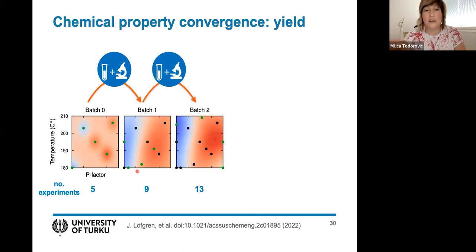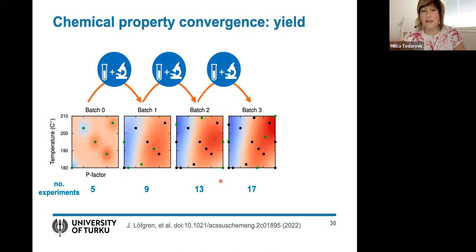So then we performed these four experiments, we added it to the model, and now you can see how this model differs from the previous one. The area of high yield is basically moving up in parameter space. So once again, the black points are now the old data, and the next samples should be evaluated at the green points. So we did these four experiments again, and now we had 17 experimental data points.